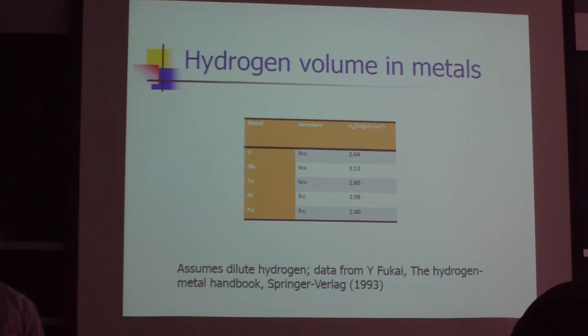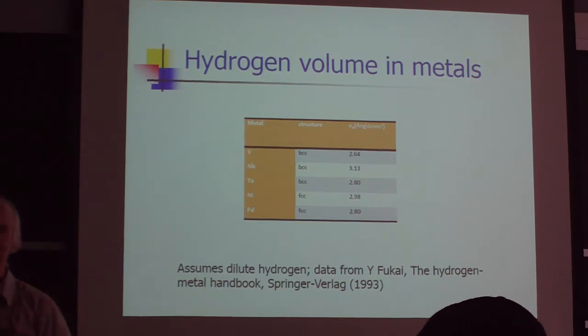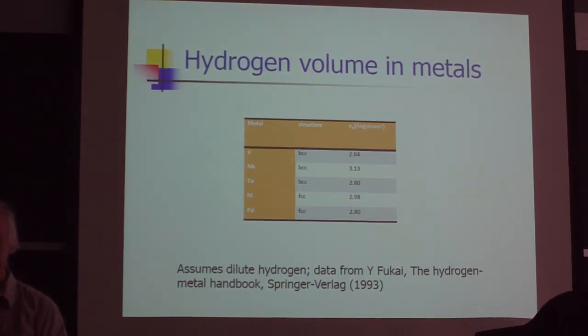How is temperature affecting the volume? Do these volumetric expansions due to loading also need to be considered in terms of temperature? Certainly, if you take palladium and you freeze it to near absolute zero or even at room temperature, there's a minor increase. I found some papers that talk about the effect. I think it's on the order of a hundredth of an angstrom. Temperature's not really a factor in this volume change.